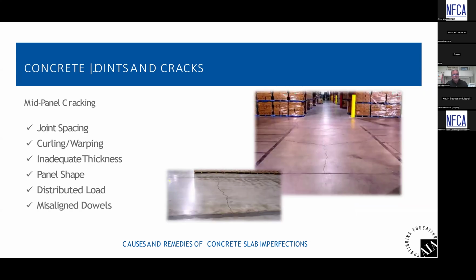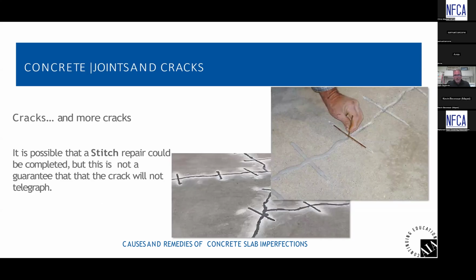How deep are those cuts for the stitching? Looks like they're about 1/4 inch or so. Yeah, it all depends on the material that you're using. If you get into something small like you see here, it might be a 1/4 inch or so, but if you get into some of the smaller rebar, they may be a 1/2 inch wide or so, and maybe down towards 1 inch deep, depending on the width and the thickness of the rebar.